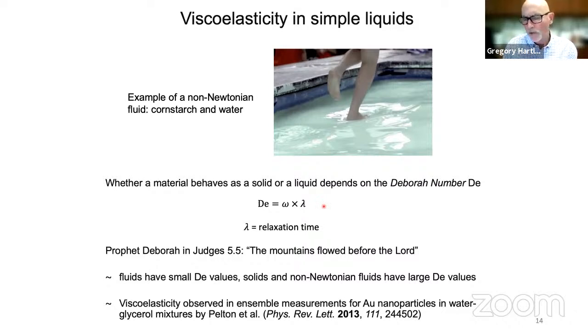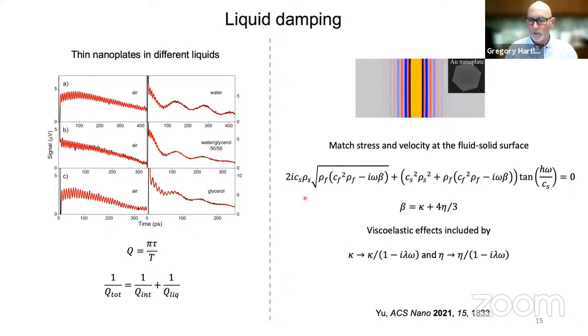So the idea of these experiments was that the breathing modes of nanostructures are very high frequency if you make the dimensions of the structure small enough. We hoped that we would be able to see viscoelasticity in simple liquids if we could make the frequencies high enough, even in liquids that had short relaxation times. To do this experiment, you need large quality factors so you can measure things accurately, and you need very high frequencies. The experiments were done by Yu, and if you can believe that, I did the theory. These are some very thin nanoplates that have very high frequencies and high quality factors. What Yu did in these experiments is he measured the frequencies and quality factors in air.